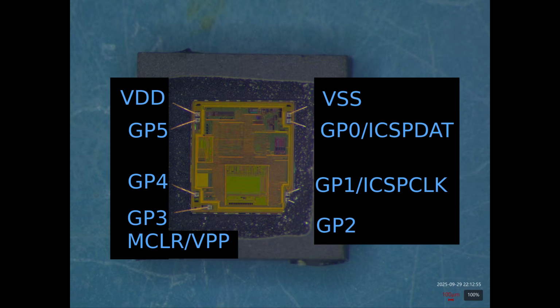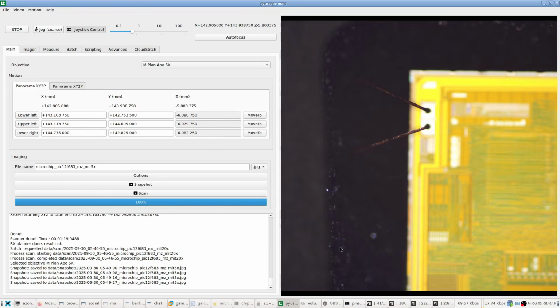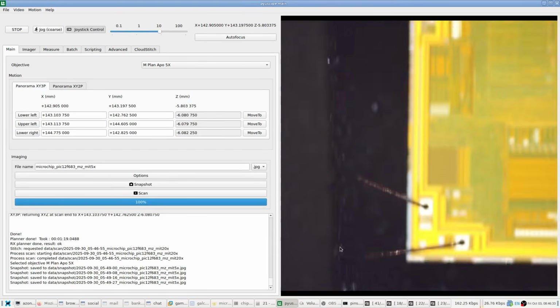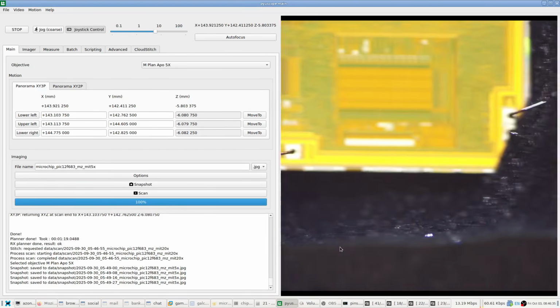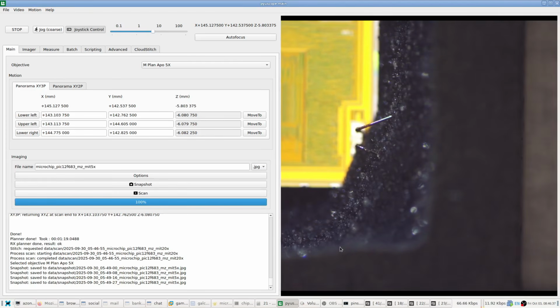But with my more refined technique, the package is much more intact, and we can actually still read some of the laser markings to tell which pin is which, which gives us this pinout map. So after a couple of seconds of sonication in Micro 90 detergent solution to get the last of the packaging residue off, here we are under the metallurgical microscope. At the moment, I've got some low angle illumination turned on as well, so we can see the wire bonds a little bit better. And we can see they are intact. There's actually still a little bit of palladium on this one.